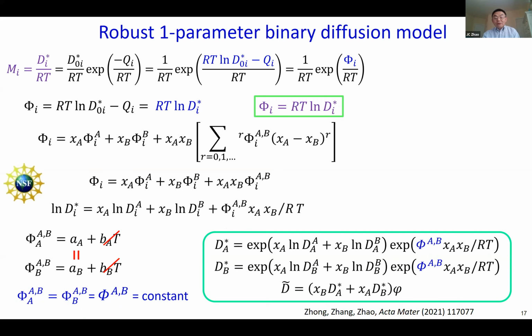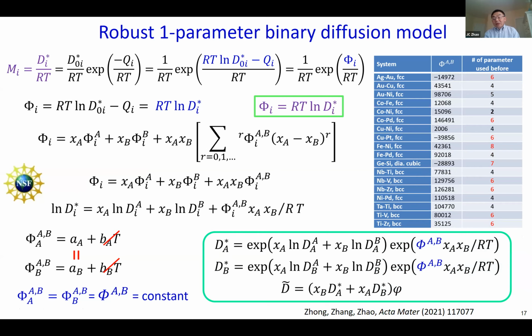So this is the self-diffusion coefficient of A in A and A in B, that's the impurity, and this is the self-diffusion of B and the impurity of B. Every system is like this. So the entire tracer data can be described from 1 parameter, and the interdiffusion coefficient can be computed after you get that. So that's how effective it is. Basically, we can describe the behavior of the entire binary solid solution system by a single parameter.